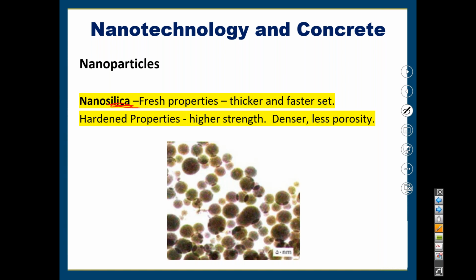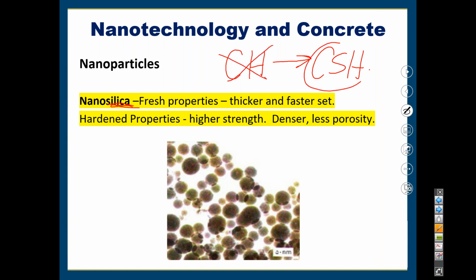Well, the nanosilica used in a colloidal form will actually react and create a denser matrix by doing three things, basically. It has a filler effect, right? Much like fly ash or slag, where it reacts with the CH to create more CSH, right? So it reacts with the not as good stuff, gets rid of it, and then creates more of the good stuff, which is always good. And this was what fly ash does, and slag, and other pozzolans and hydraulic SCMs.